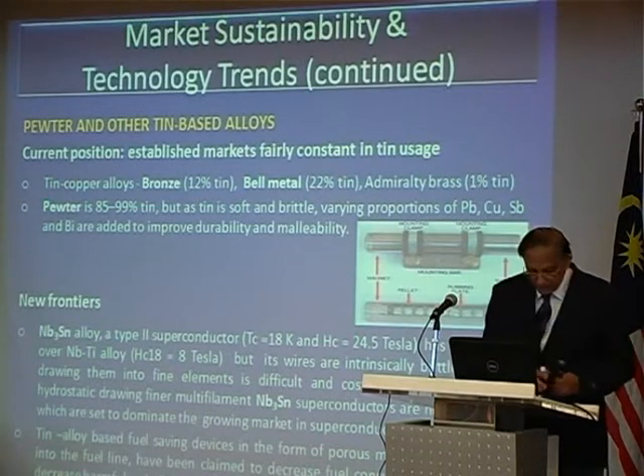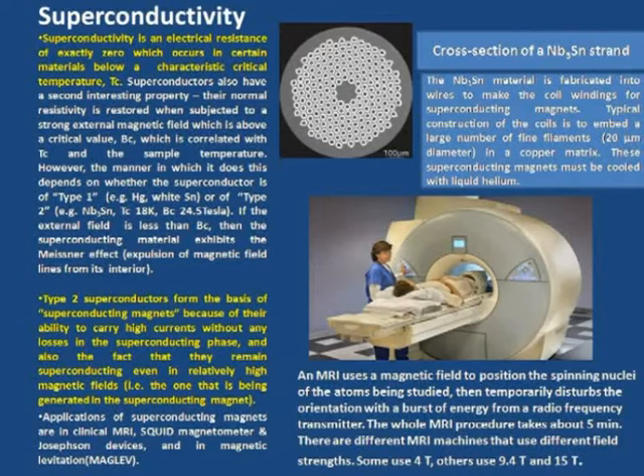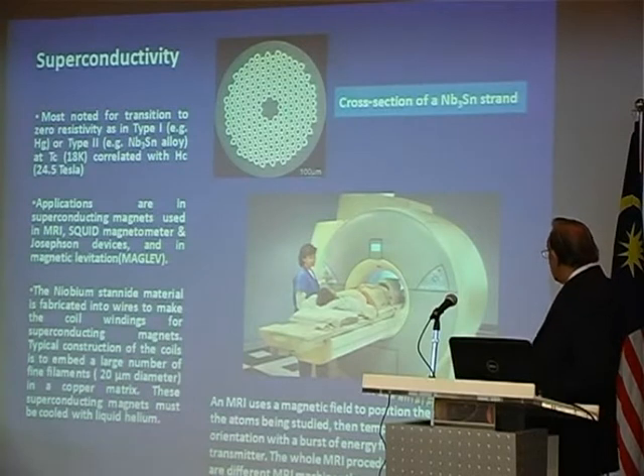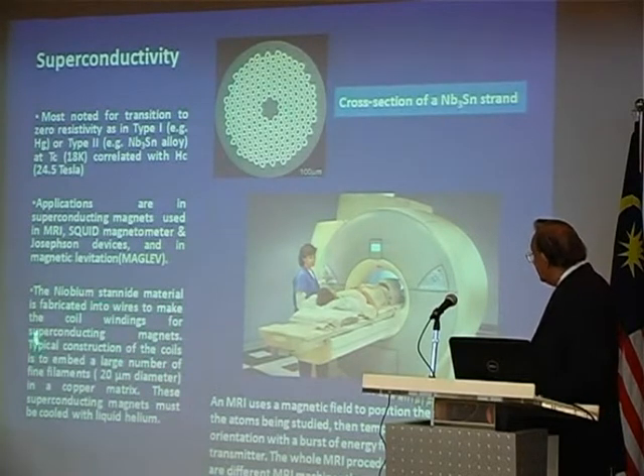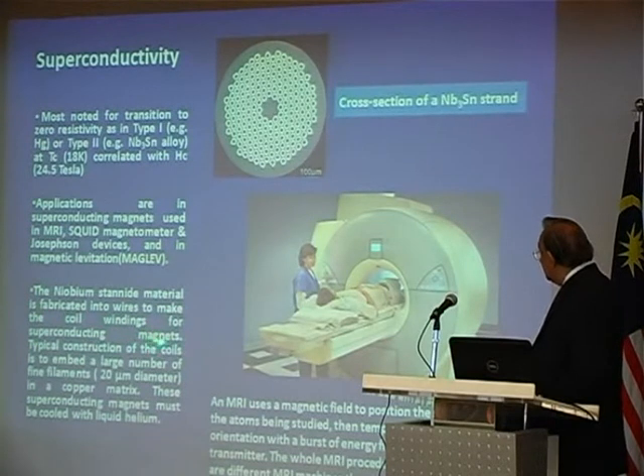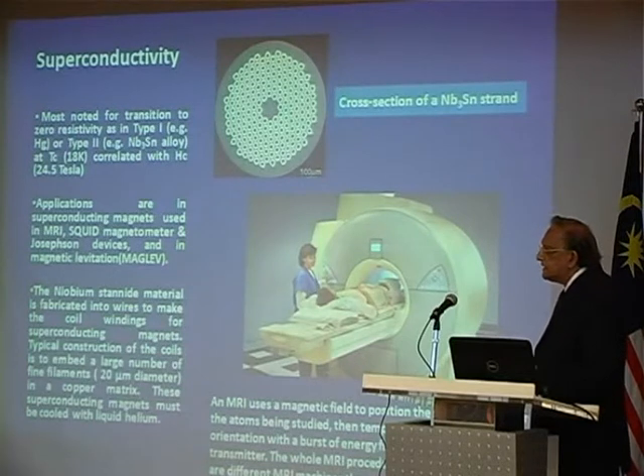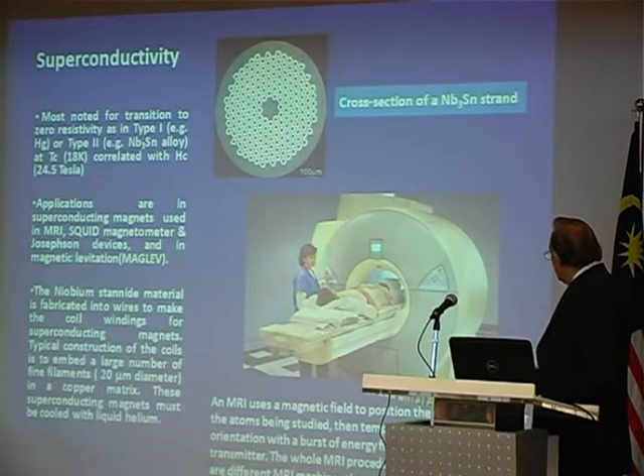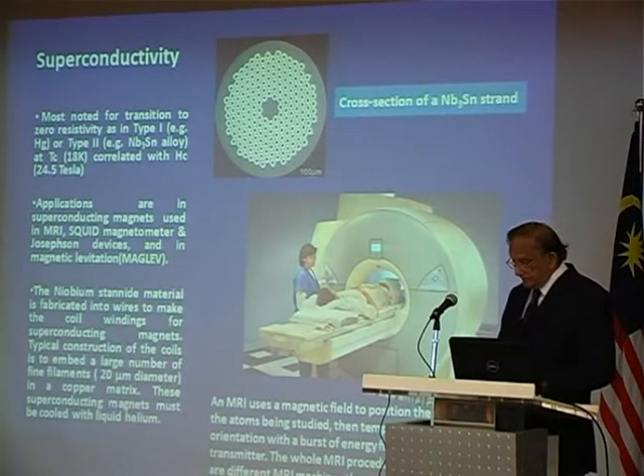Nowadays, maybe I can go to the next slide to show you, in MRI, magnetic resonance imaging, for example, you use superconductors and you need these coils. So niobium coil windings on the electromagnets there. The problem originally was they were too brittle. Now a special technique has been developed to draw them, which is cold drawing. So this allows a window of opportunity, and now niobium tin is set to conquer the market here. And you can see that in MRI, they use 4 Tesla, 9, 15 Tesla. So you need a material like niobium tin.